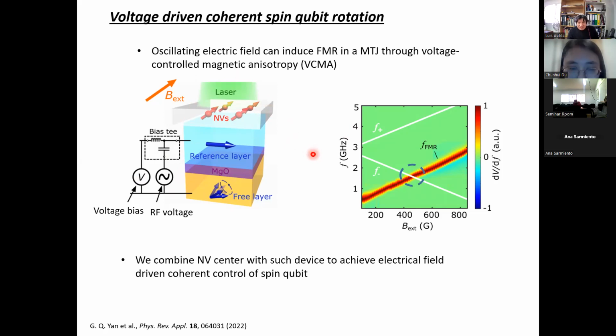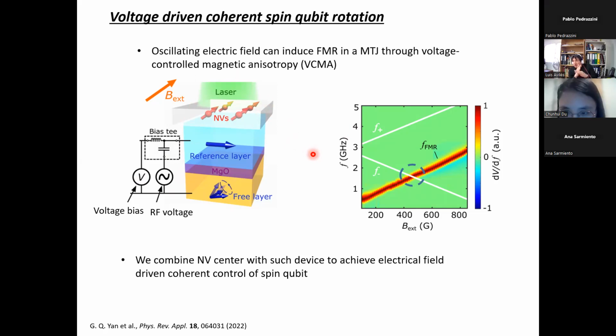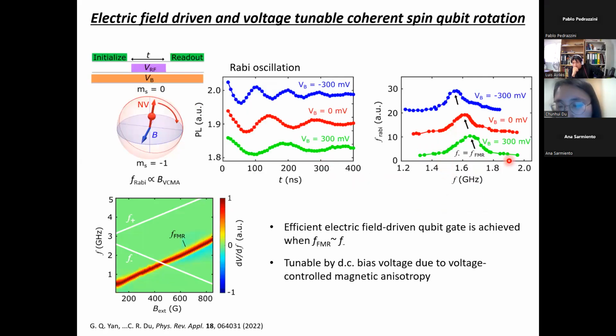Now that you give more details about this, Chunhui, when you change your magnetic field, you will lose your signal, right? So you will only have one magnetic field value to detect. So it's a very good point. What we do is we vary the magnetic field, so this varies the NV electron spin resonance frequency. You can see that when the frequency matches the FMR frequency, we see a peak, and if it's away from it, we see the Rabi oscillation decrease. It's not very narrow because the width of the FMR, I think, is like 100, 200 megahertz.